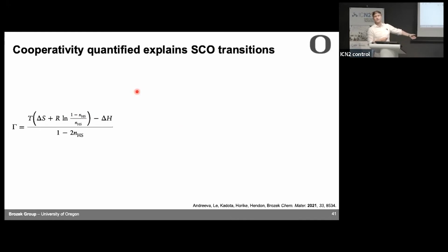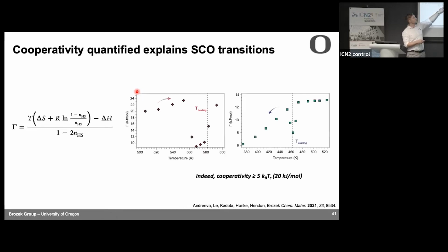I was wondering, what the heck is cooperativity? Well, it turns out you can measure it from the data. Cooperativity people often call gamma. The entropy and the enthalpy of your spin crossover, you can get that from calorimetry. So if you have differential scanning calorimeters, you can measure that. The only thing you actually need is, at a given temperature, how many of the metal sites are in the high spin state. That's all you need. And so we can take someone else's data that they collected for this MOF, and we can figure out what gamma is.